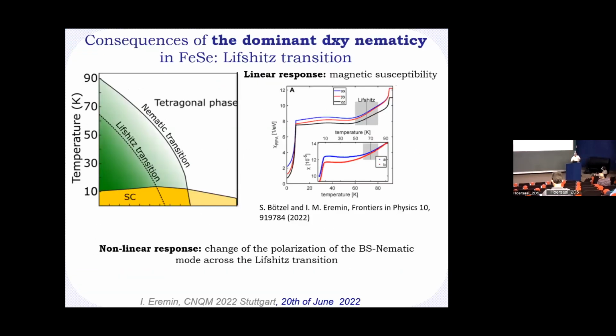Okay, so now my last slide is basically this one. If you now want to distinguish between scenario A and scenario B, one of the important consequences of scenario B is that you necessarily expect that as a function of temperature or doping, in addition to the nematic transition, you also have a Lifshitz transition where this XY dominated electron pocket shifts away from the Fermi level. And there are a number of experiments that are in favor of this.